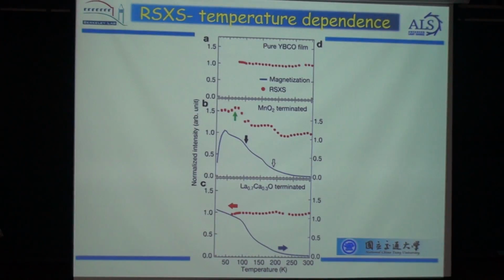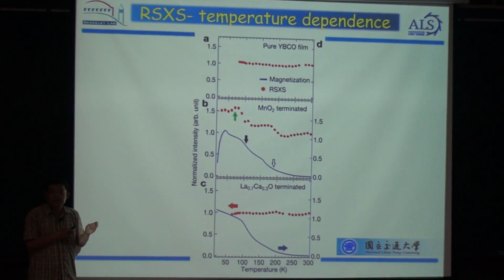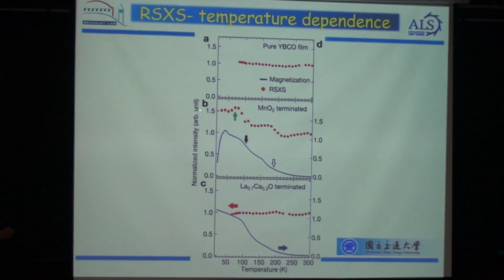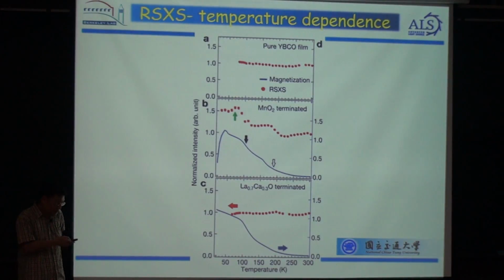But just remember that copper is in YBCO, which is the superconducting material. And for this sample, the superconducting temperature is around 70 Kelvin. So actually, we see some ferromagnetic order, even if it is a very weak order, within the superconducting phase of this YBCO, induced by this bilayer. Okay, and this is new. For another termination, you can see that we see nothing. So we made 3 experiments, and we can distinguish no ordering and magnetic ordering in copper. The emphasis is on the order in copper.